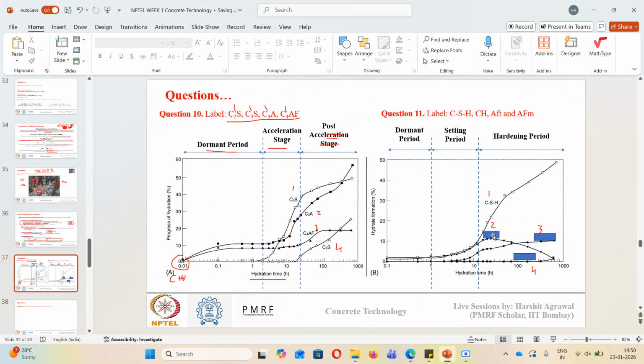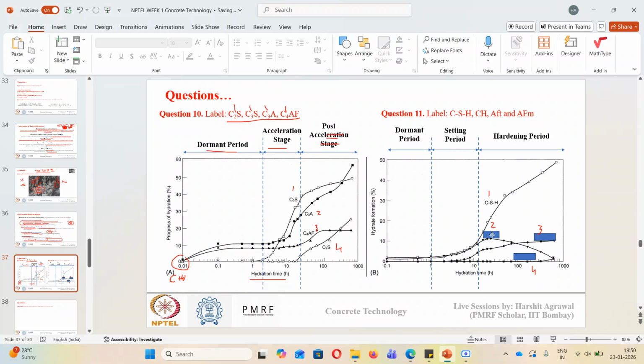Second one: you can see initially it formed, it grew over time, and then it declined in the hardened period. So it is AFT. Ettringite starts to convert into monosulfate, so the quantity of ettringite starts to drop as monosulfate formation increases.